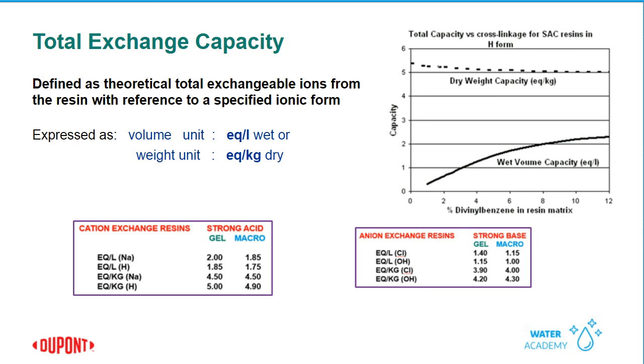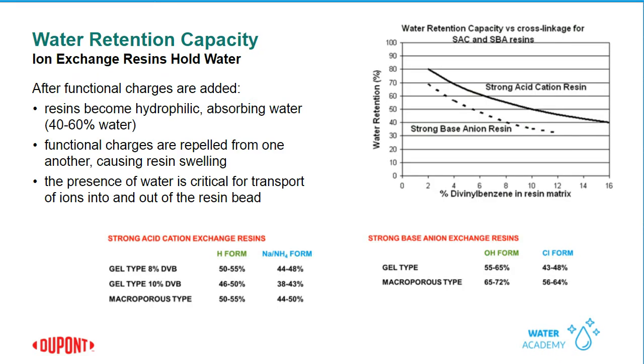Okay, let's talk about another type of capacity that the resins have, and that's the ability to hold water. We call this the water retention capacity. You may have also heard it called moisture holding capacity, but basically it's how much water the resin holds on to. After the resin copolymer is made and the resin becomes functionalized, then it starts to take on water. The amount of water that it takes on, because it has become hydrophilic, really depends on the functional group that was added, the ionic form that it's in, how many waters of hydration are associated with that, also the percent DVB level.